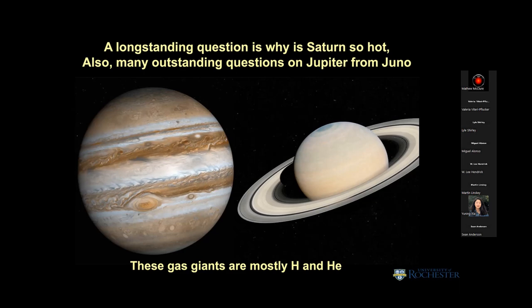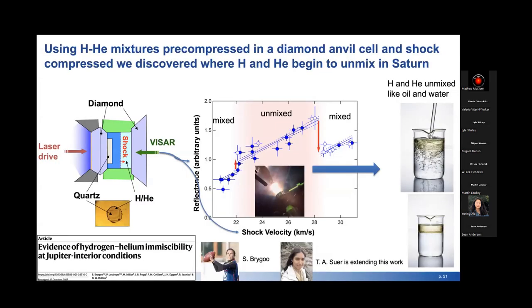and drains down into the interior. So we did some experiments where we essentially take a diamond cell and we pre-compress helium and hydrogen, and then we launched compression waves through it and found this reflectance change. I could also plot temperature. A big jump here and a big jump here. And we worked with theoretical calculations to help us unravel what this means.